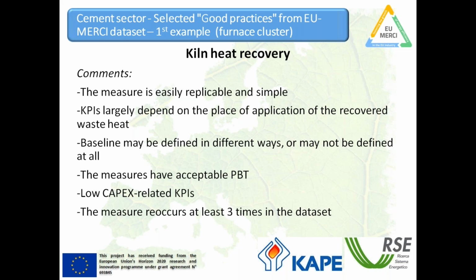The KPIs of the good practice of kiln heat recovery are hard to define on average, because the baselines and energy savings often depend on the place of application of the recovered waste heat. So sometimes energy savings in different parts of the factory are reported as a result of the heat recovery. The heat recovery measures from kilns have very acceptable payback times, and the capex is not so high, so the capex related KPIs are also not high. The measure reoccurs at least 3 times in the whole data set.